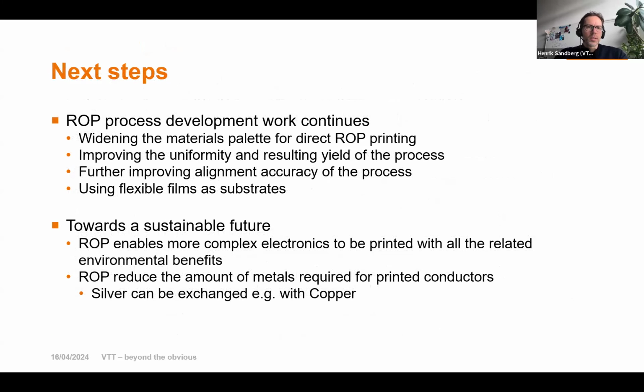So the next step is really to work on continuous optimizing of the process, but also together with partners develop more and more materials. The sustainability aspect of this method is that we can do additive on very thin or on flexible substrates in very thin layers. So the amount of silver, for example, if we use silver ink, is really small. So that also helps very much if you look at the sustainability budget.